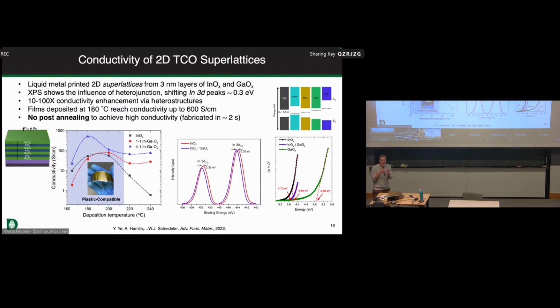Oxides, because they're transparent, are also really important for a number of sensors. If you want to make, for example, a photodetector or another device, it often has to have a transparent electrode or a window electrode to allow the light in. A solar cell has the same challenge. In our case, by using this heterostructure, we can enhance the conductivity of that indium oxide by a large degree, about 10 to 100x typically.